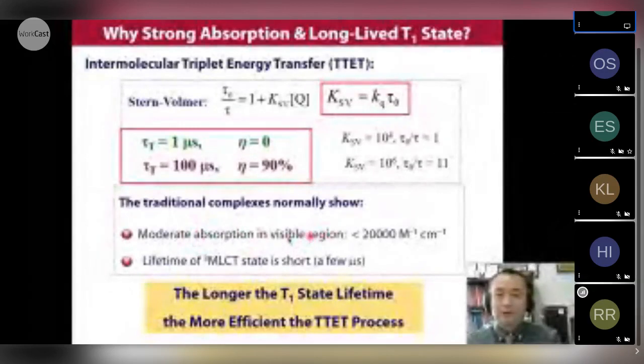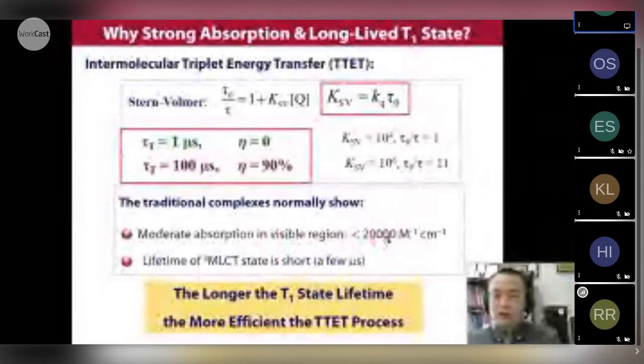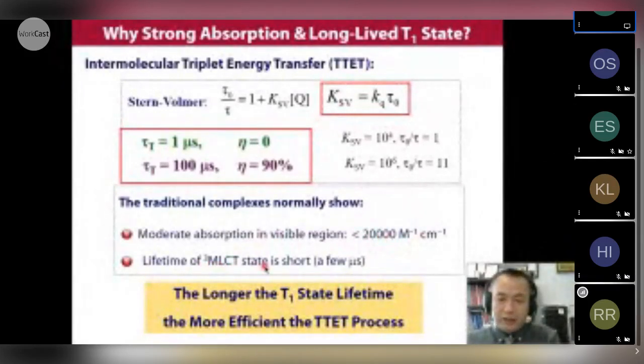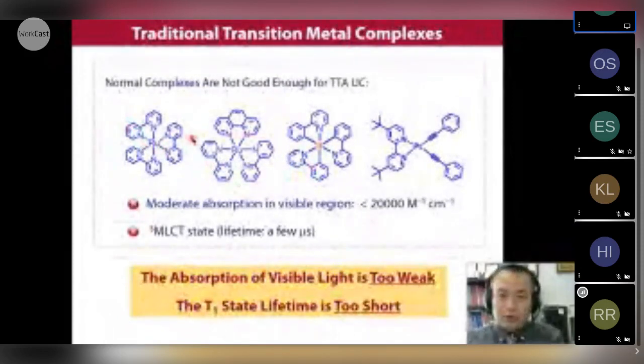But for the conventional metal complexes, the absorption in visible region is usually very weak. So the molar absorption coefficient is less than 20,000. So it's not strong compared to organic chromophores. The triplet lifetime is also short. It's only a few microseconds. It's much longer than fluorescence lifetime, but this lifetime is still not long enough for a better application in photocatalysis or upconversion. So these are the typical traditional metal complexes.